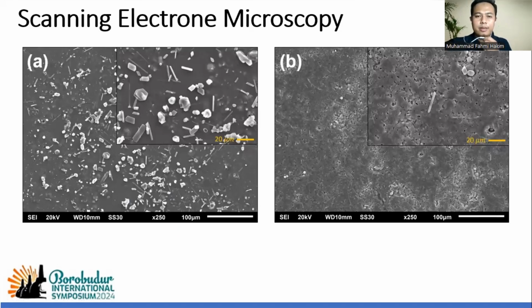Okay, next, this is about scanning electron microscopy. You can see the pictures. There are two pictures. The morphology and elemental composition of 10% sulfonated polyether ketone with aluminum oxide membranes were examined via scanning electron microscopy. We can see that the 10% aluminum oxide was mixed, forming a composite membrane. This is like aluminum oxide in the matrix of the polymer polyether ketone. SEM revealed the morphology and elemental composition inside the membranes, which in turn reflect the membrane's absorption ability and proton conductivity.